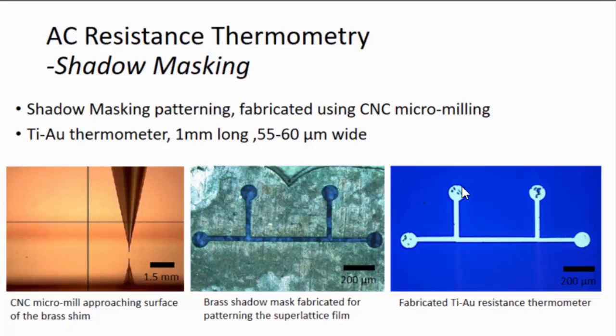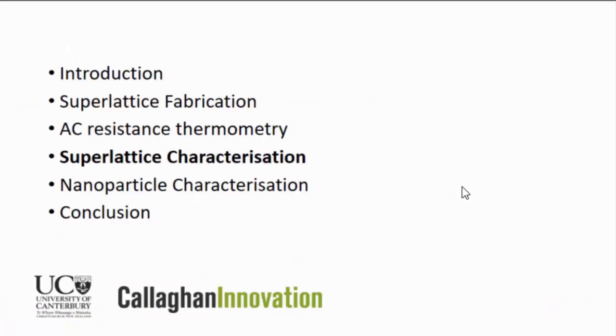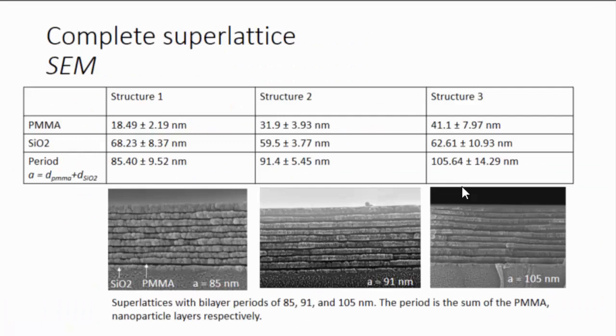So here are some SEM micrographs of what our superlattice ended up like. We studied 3 different periodicities, which ranged between 85 nanometers at the low end and 105 nanometers at the high end. We had a little bit of an issue in that because the silicon dioxide nanoparticles are porous, the PMMA solution would tend to flow into it. And so across all of our different architectures, we did see a reduced PMMA thickness, which possibly has broken the periodicity a little bit.